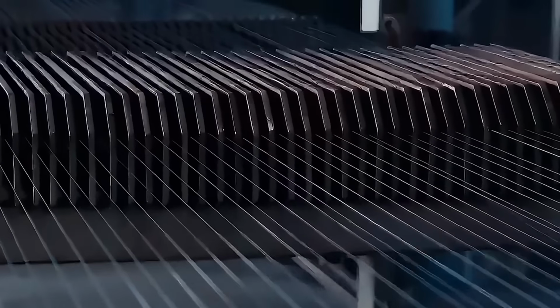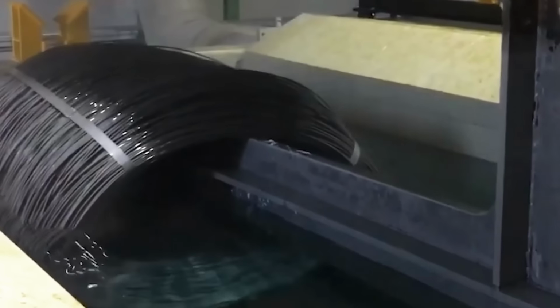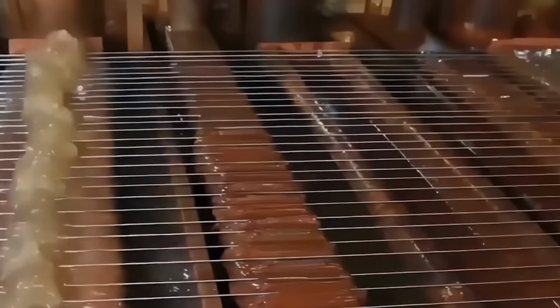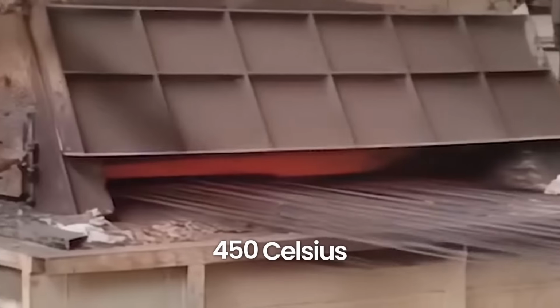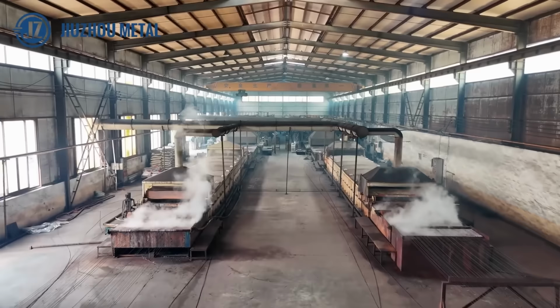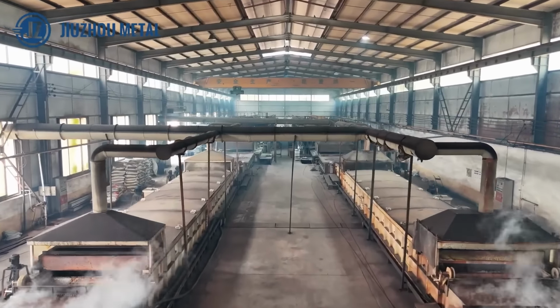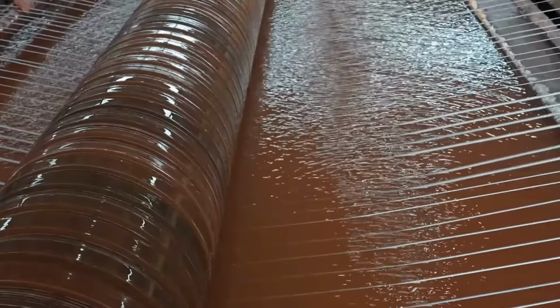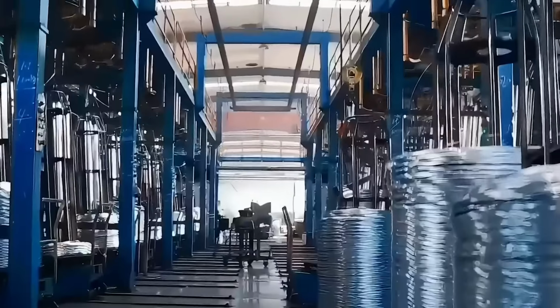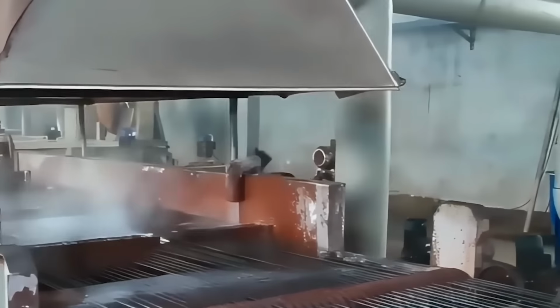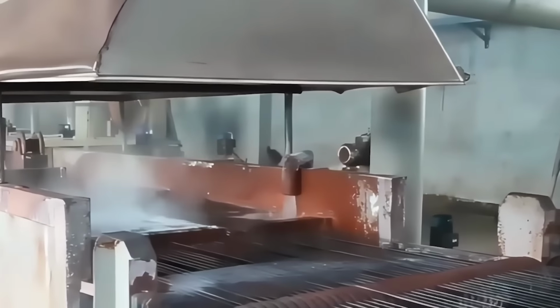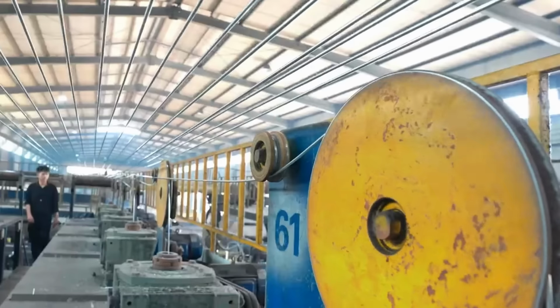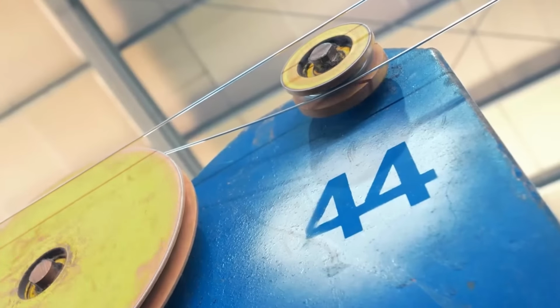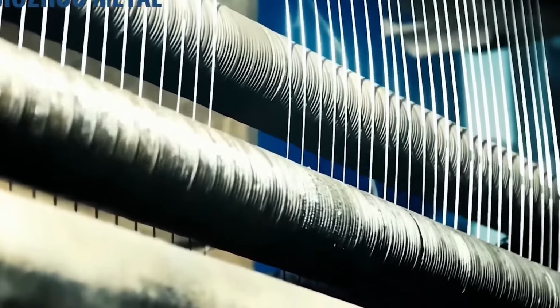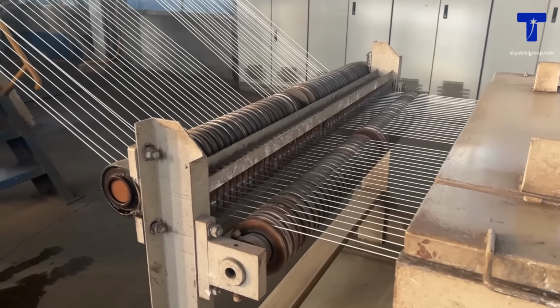The wire first passes through a cleaning bath that removes any residual oil or oxide. Then it's immersed in molten zinc at around 450 degrees Celsius. The zinc doesn't just coat the surface, it actually bonds metallurgically with the steel, forming a series of zinc-iron alloy layers. When the wire emerges and cools, it has a bright, silvery appearance and a protective layer that can last for decades, even in harsh environments.